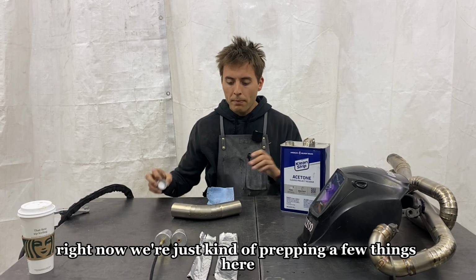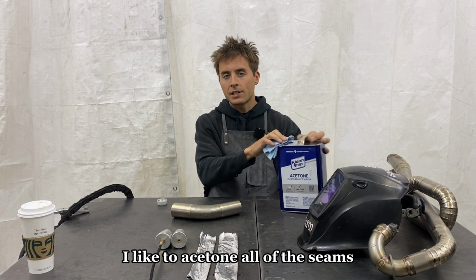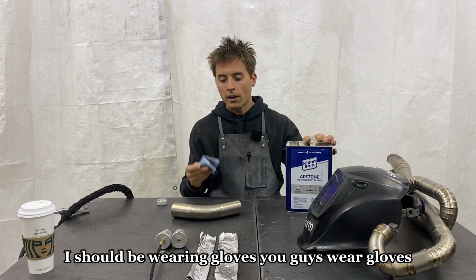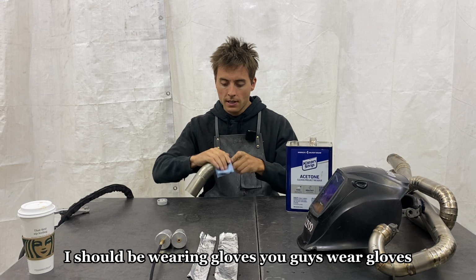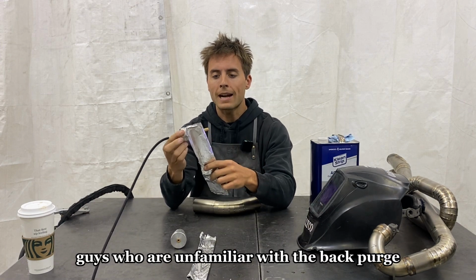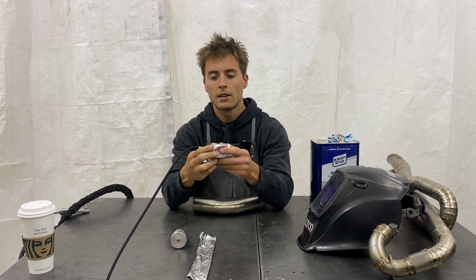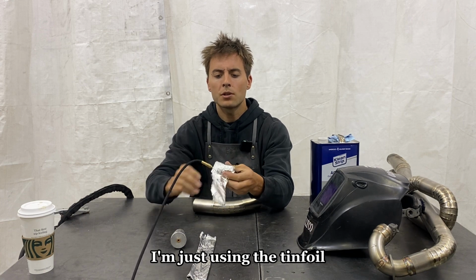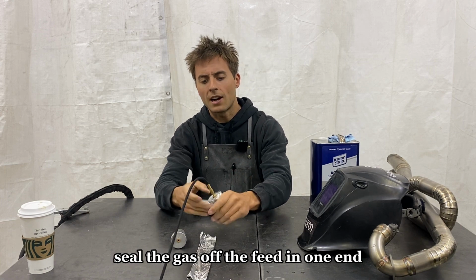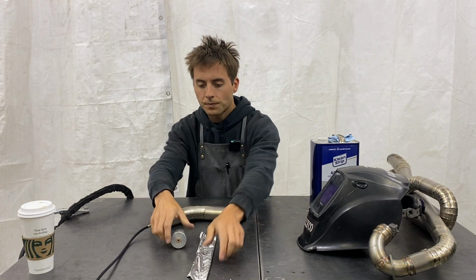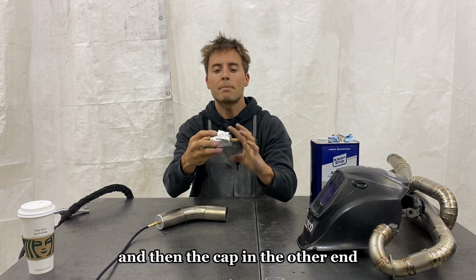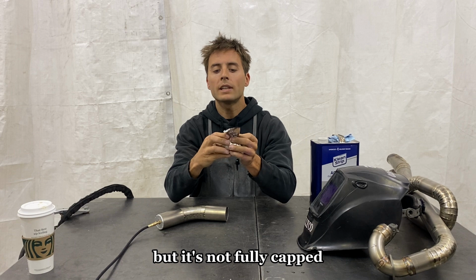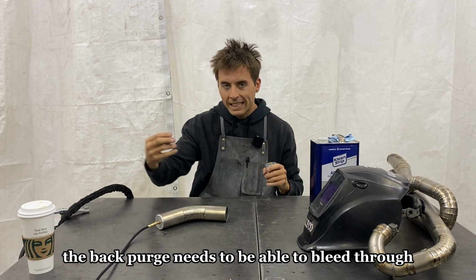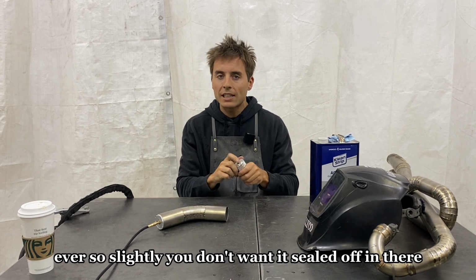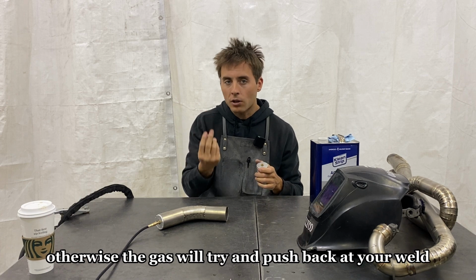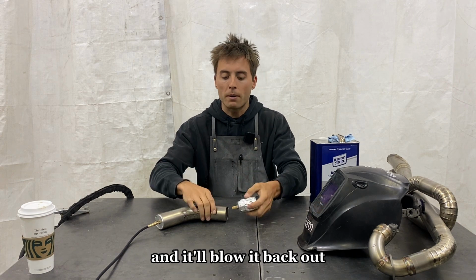Right now, we're just prepping a few things here. I like to acetone all of the seams. I should be wearing gloves. You guys wear gloves. Next, for those who are unfamiliar with the back purge, you'll be able to see here what that looks like. I'm just using tin foil to seal the gas off, the feed in one end, and then the cap in the other end. But it's not fully capped. The back purge needs to be able to bleed through ever so slightly. You don't want it sealed off in there. Otherwise, the gas will try and push back at your weld and it'll blow it back out.